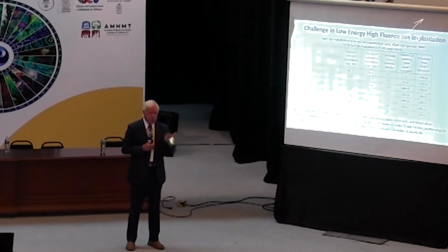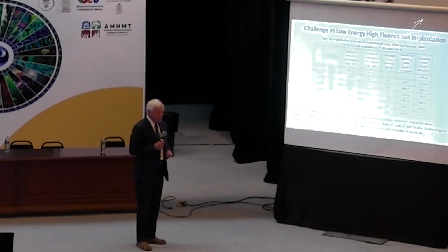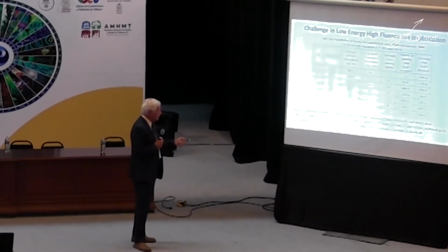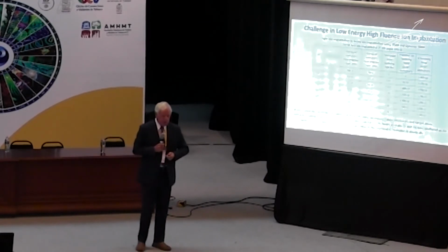And what happens with the larger ions is you get more sputtering. So for hydrogen, there's no sputtering. It just goes into the material. You can hardly sputter a silicon atom with a hydrogen atom. But you get on down here with silicon on silicon, or iron on silicon, or silver, gold, you can sputter a lot of the surface away, a lot of the silicon substrate.